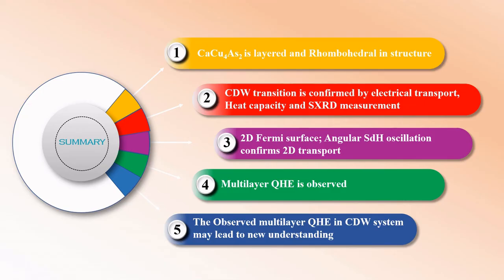In short summary, calcium copper four arsenic two has a rhombohedral layered structure. All electrical transport, specific heat, and X-ray diffraction experiments confirm charge density wave in the system. 2D transport promotes quantum Hall effect in the system. Most importantly, quantum Hall effect in charge density wave bulk system is a first, and it enlightens new understanding of charge transport.